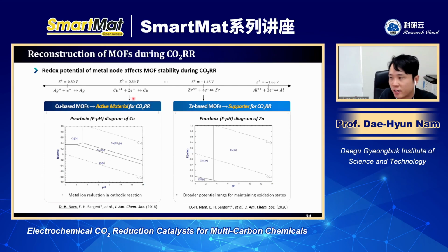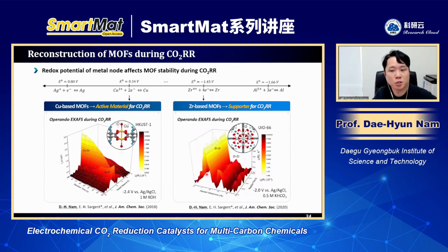In the case of copper, this is a very reductive metal. It is very easy to be reduced. So in this potential range, metallic copper is the stable one. But zirconium is less reductive than copper. It means it is a relatively oxidative metal. So zirconium prefers to exist as positively charged ions in this potential range. In this way, I think the reconstruction of the MOF would be different according to the type of metal.